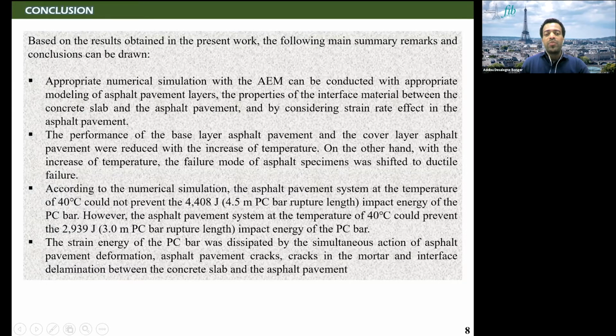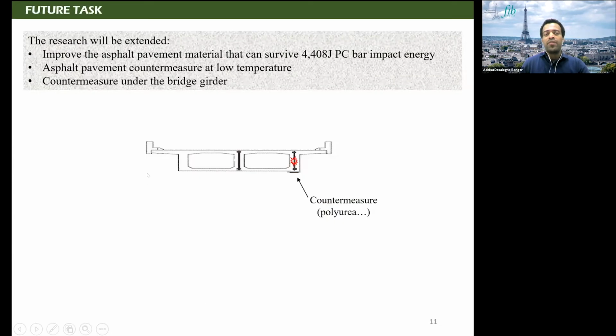Finally, the strain energy of the PC bar was dissipated by the simultaneous action of asphalt pavement deformation, asphalt pavement cracking, cracking in the mortar, and interface bond delamination between the concrete slab and asphalt pavement. So in the future, we will improve the asphalt pavement materials so they can survive this much, 4,408 joule impact energy. And the asphalt pavement countermeasure at low temperature will also be carried out.